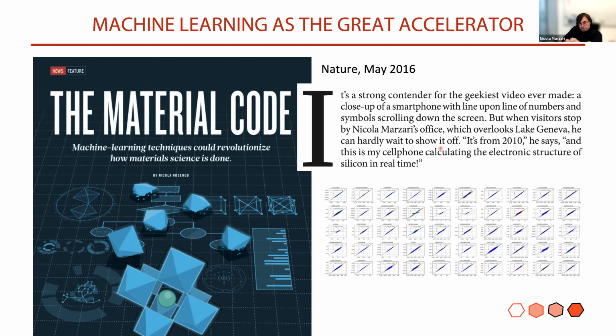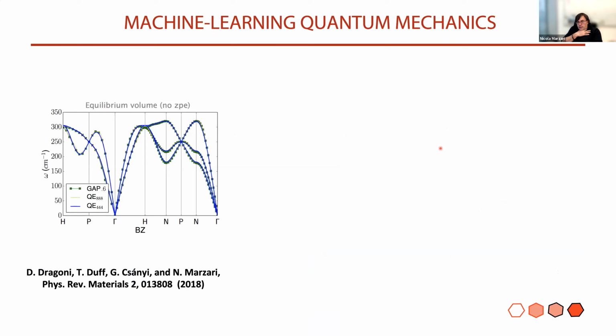And in this, what we need to figure out is actually the diffusion characteristics of lithium ions in a solid state matrix. And that's a process that is very slow. We can't do it with brute force of first principle molecular dynamics. And so what we do is we machine learn the potential energy surface with neural network and with kernel regression